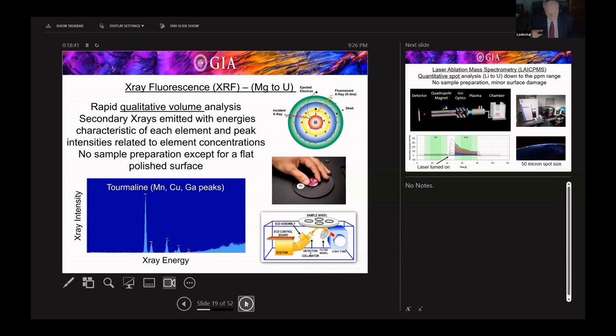The graph at the bottom is just what you'd see on our monitor, on our screen at the instrument. And you see these light blue peaks. The peaks are at particular energies, which are characteristic of the major, minor, and trace elements in the material. And the intensities, the heights of the peaks, are somewhat related to concentration. But this offers a quick, non-destructive analysis. All you need is a polished flat surface to get a quick idea of particularly the color-causing trace elements that are present in many colored stones. And this is a tourmaline. It's one of these copper tourmalines. It's got manganese, copper, and gallium peaks. But this is where we start in terms of doing a chemical analysis.